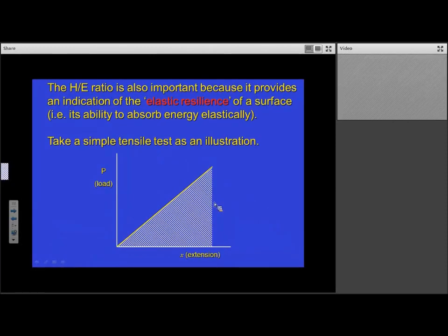There's another reason why the H over E ratio is important. It's because it provides an indication of something that we call the elastic resilience of a surface. That's its ability to absorb energy elastically. So if you take a simple tensile test as an illustration, you pull this tensile test piece up to a maximum load of P and an extension of X. The energy which is absorbed elastically in that is the area under that curve. In a way, if you think of it simply, it's the average force times the distance moved is the work you put in. So the energy absorbed is that area, half P times X.